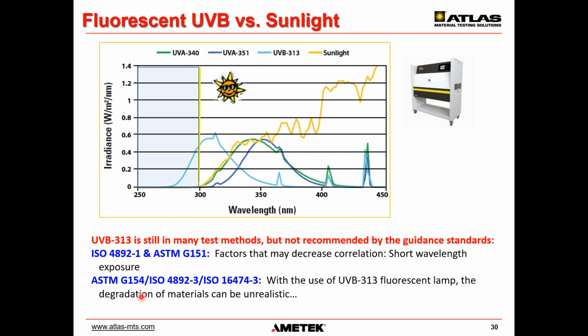The primary fluorescent UV standards, as shown in blue here at the bottom, are ISO 4892, ASTM G151, and G154, which are the general standards, and ISO 4892 part 3 and ISO 16474 part 3 for paints and coatings. These are the fluorescent standards. They specifically caution that UVB 313 lamps should not be used for weathering purposes. You see the 340 lamp here is much better in the solar cut-on region than the unrealistic radiation 313 lamp.